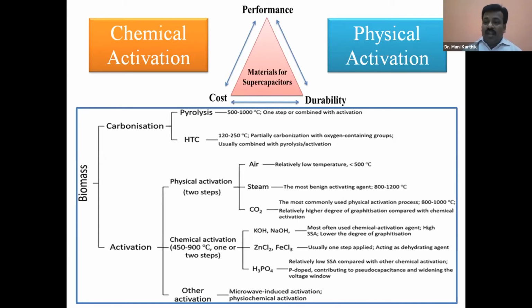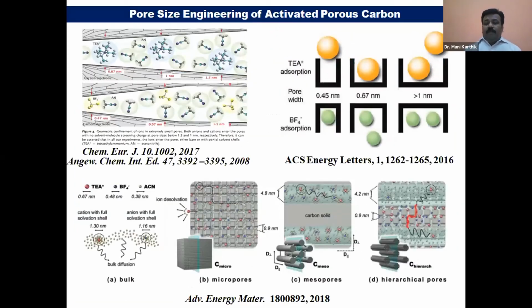That's the reason Kuraray, a Japan company, is making the activated carbon. They are a major supplier for Maxwell supercapacitors. So here, everyone, this chemistry is very simple, but really this chemistry is not very simple. You need to fine tune your carbon according to which electrolyte you are using. You can see these papers explain very nicely the correlation between the pore size as well as the ionic size of your electrolyte.